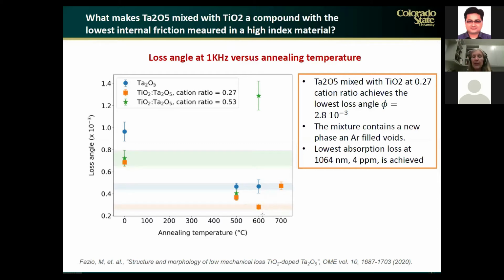Just to give you an idea, these coatings that go into the mass of the interferometers have been optimized also with respect to absorption loss, because absorption loss also will cause noise in the interferometer. And the best results that have been obtained in terms of absorption loss at 1064 nanometers are 0.5 parts per million, which is an absolute record low.